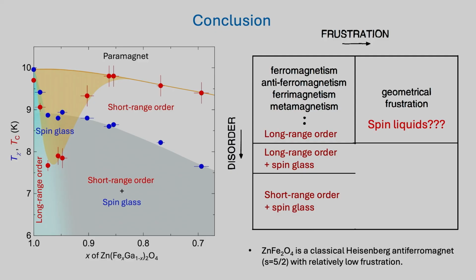Now we come to the conclusion of my talk. You can understand this phase diagram very well now. There's a spin glass phase, and independently there are the long-range order and the short-range order happening in this system. And they are rather uncorrelated, but they are characterized by different measurement techniques. Now, if you come to this roadmap for our search of the spin liquid, then you understand that if the system has very little frustration, you are mostly along this direction. You have long-range order and spin glass, and short-range order and spin glass.